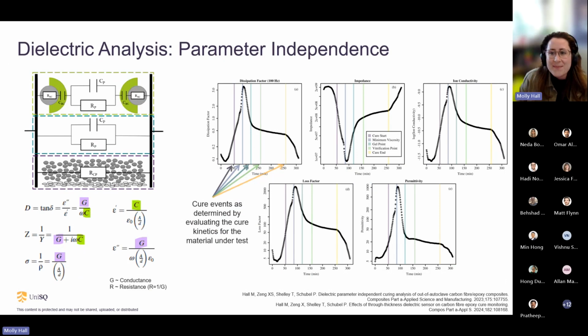And essentially, we can. So here's from one signal, from one cure, here's all 5 dielectric parameters. And what I've done is overlay the cure events that we know from simulating that specific cure from the temperature reading that we collected. So what you're seeing here is that, for example, this blue line is our minimum viscosity. All of these parameters sort of have the exact same trend. They hit their peak or their global minima at the same point. They increase at the same point. They end at the same point. So this was a really useful finding, that we can use all of these parameters interchangeably.